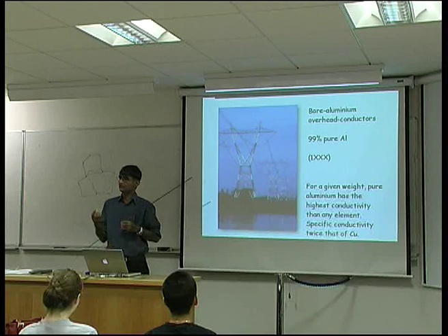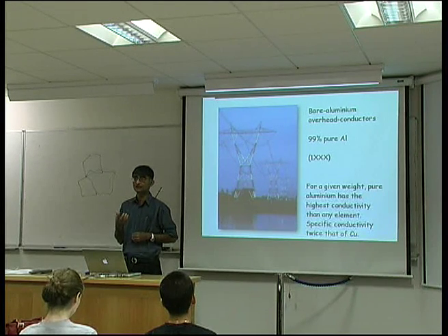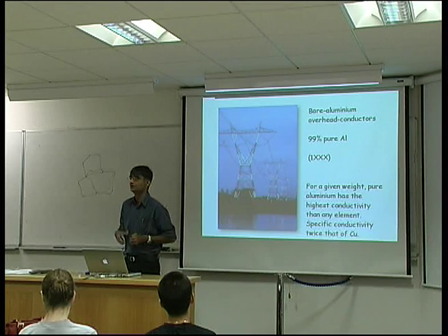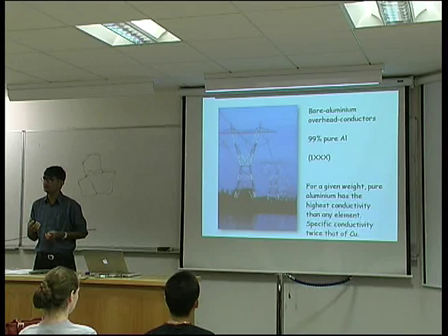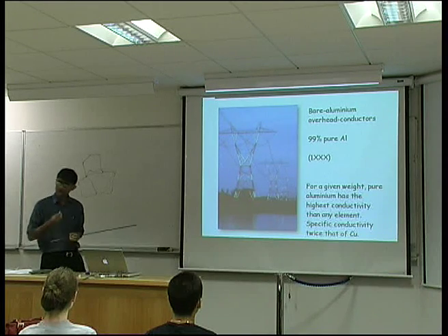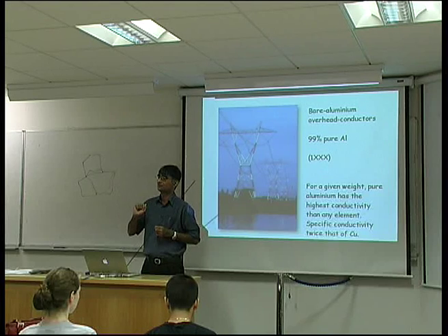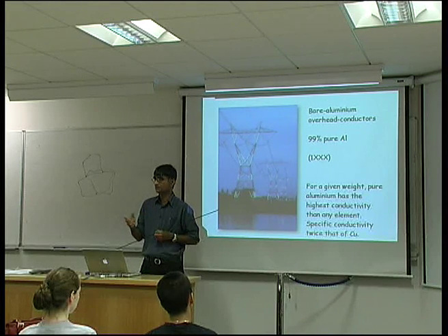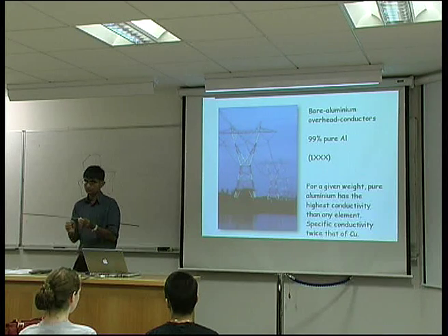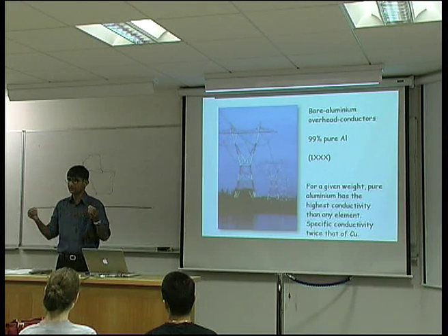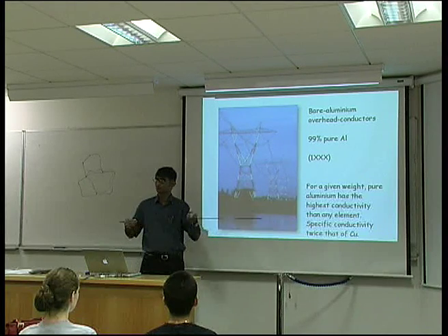Now, unfortunately, pure aluminium is not very strong. It's got a strength of about 10 megapascals. Okay? So what you do is of course you can precipitation harden it to increase its strength, but whatever you do to put impurities, if you like, inside aluminium will reduce the electrical conductivity. So, to reinforce the aluminium, you have steel wires along with the aluminium cables to provide the strength.